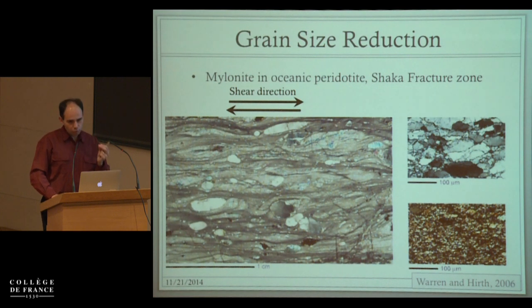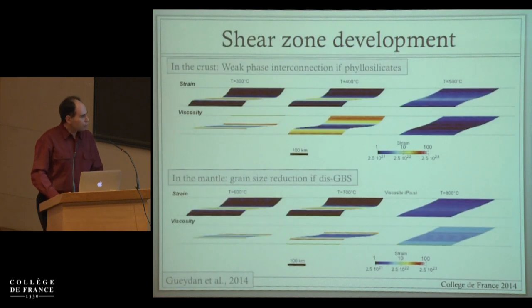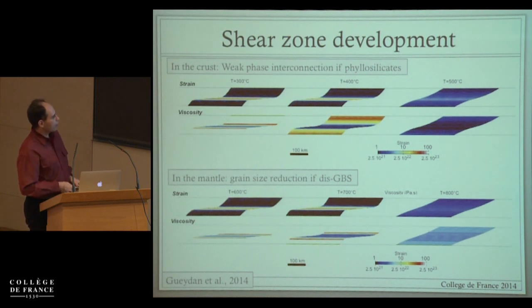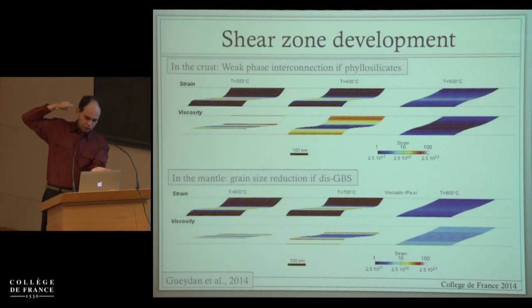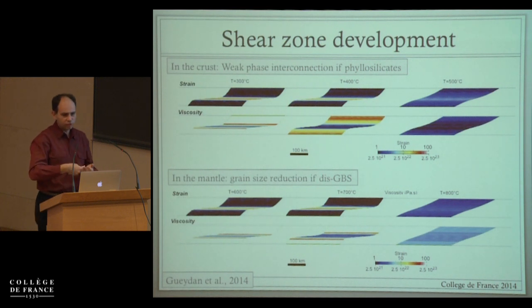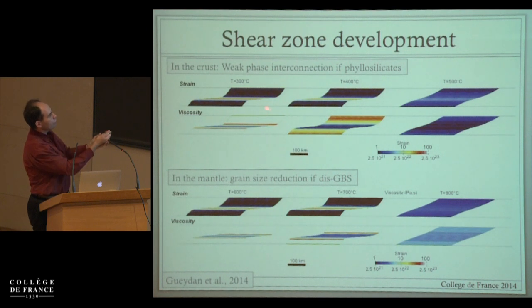And it turns out that if you have the right deformation regime, that can also produce the localization. Just giving you an example of some of the calculations we've done of these processes. This is work that was led by Frédéric Gueydan in this case. What is done is to just take a pile of synthetic rocks and shear them uniformly with some evolution law for the fabric or the grain size, and see whether you form localized shear zones, like in this case here, where you have a high strain, low viscosity band, or you don't, like in this case where the deformation is much more uniform and the strength is much more uniform. And basically he was able to map out the conditions for which you have this and for which you don't.